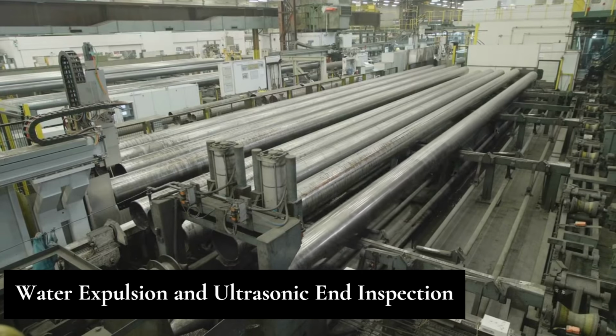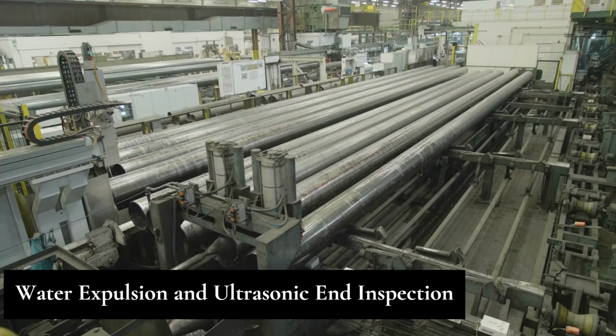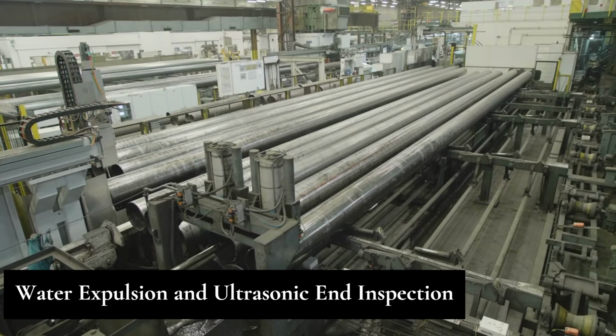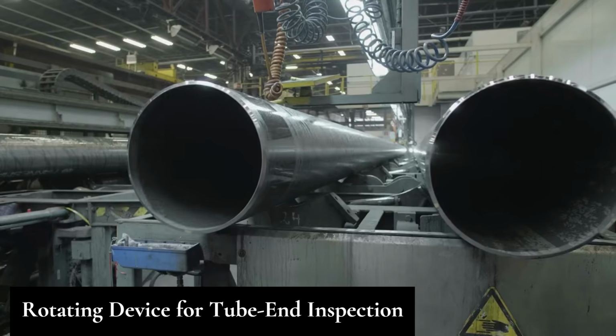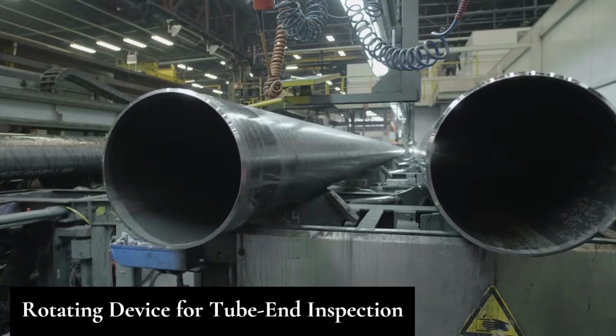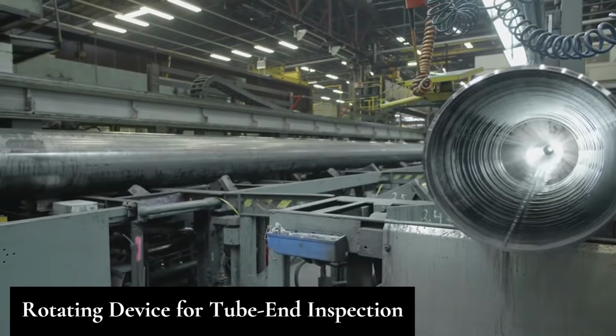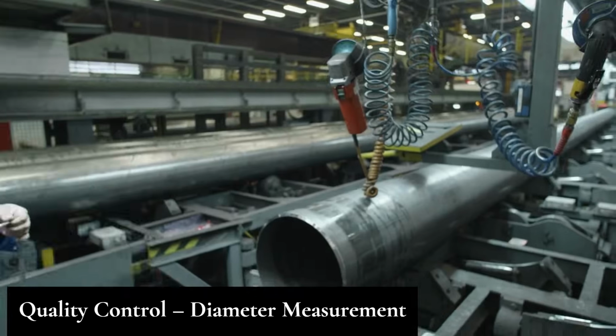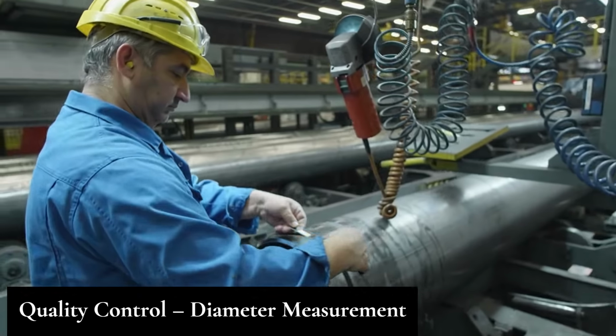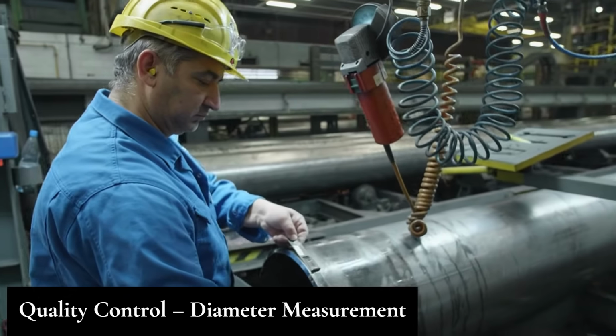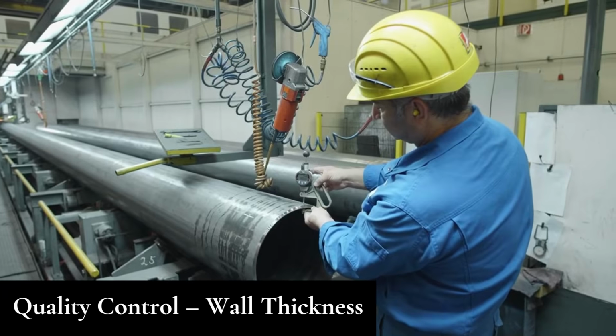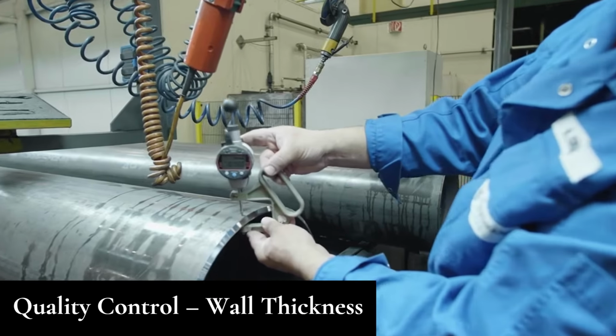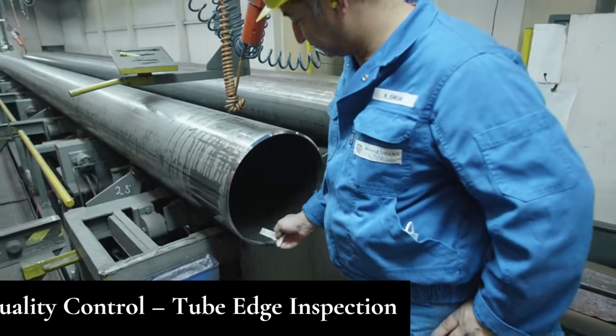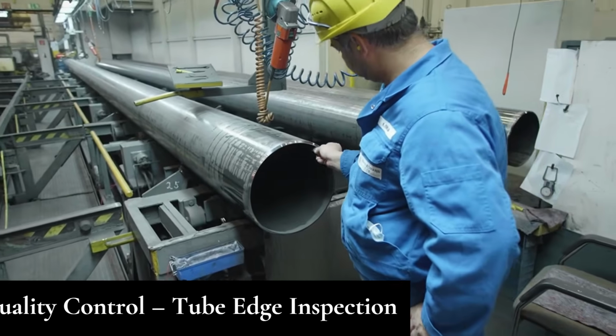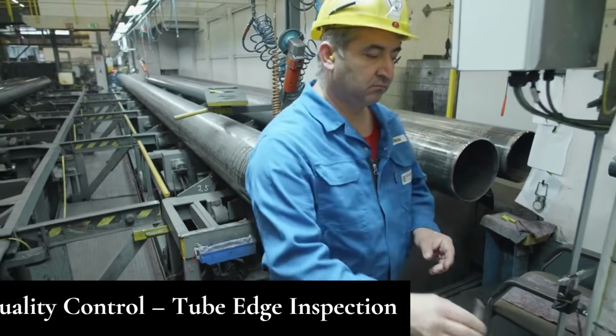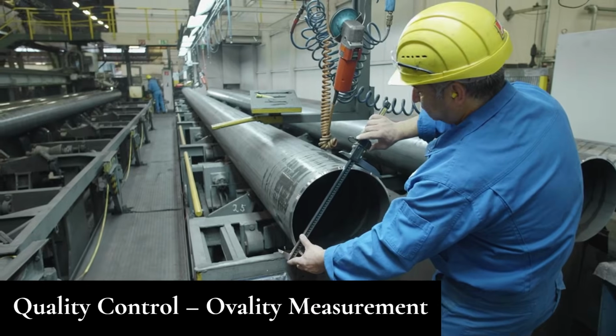Ultrasonic equipment checks the tube ends for internal flaws. Removing water ensures accurate readings. The tube is rotated to allow a complete inspection of both ends. Sensors check cut quality. Diameter gauges confirm the tube meets standard tolerances to prevent problems in assembly. Wall thickness uniformity is verified as well. Then the edges of the tube are inspected to ensure they are uniform, as well as the tube ovality.